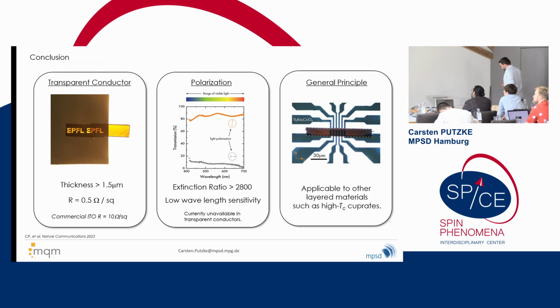And so what we found is that you now have a transparent conductor that is highly polarizing. That is just a showcase of what happens if you finite-size limit a layered material, and that you can get a differentiation between the optical conductivity in the C-axis and a very good metal in the plane, all the way to the fact that you can actually do this in high temperature superconductors. So you can now think of a material that is a transparent metal with basically no electrical resistance. And that's another technique more tailored to the application, showcasing what can be done in this case.